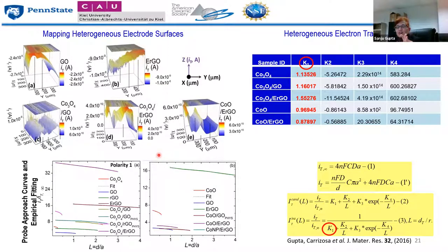It can image the electrode surfaces over a very large area. So it can map the electrochemical activity, as you can see here, in three-dimensional as well as two-dimensional, these ups and downs. Over a large area, I'm talking about like 400 or 500 micrometer by 500 micrometer square, which is pretty good compared to scanning probe microscopy like AFM, for instance, you may have heard of it. And not only can it image the electrochemical activity, but using what we call the probe approach curves, and by fitting these to a phenomenological model, we can determine what we call the heterogeneous electron transfer rate. And some of these are over here on this table I'm showing. So this is the first order electron transfer rate, the K1 coefficient, that we can determine using these probe approach curves. So the higher this K1 rate, the higher the electron transportation. And it means it's a faster and rapid transportation.